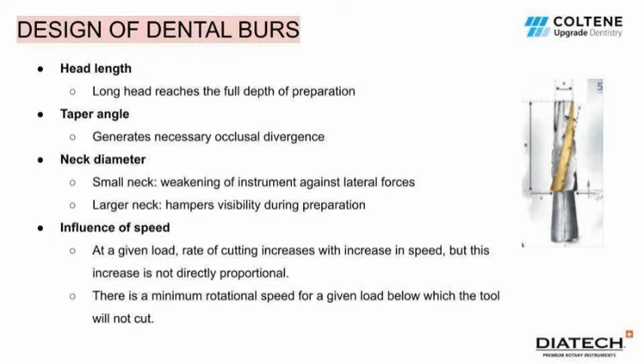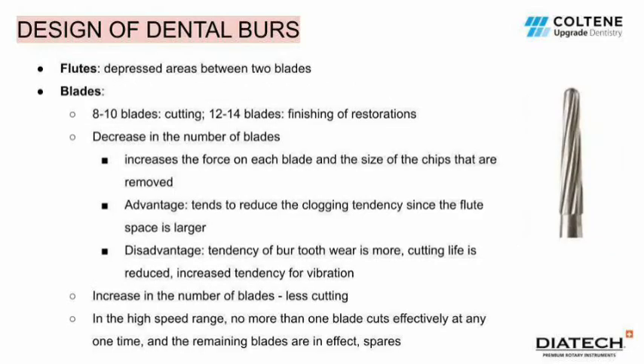After that, we have the influence of speed. At a given load, the rate of cutting increases with an increase in speed. But this increase is not directly proportional to the rate of cutting. There is a minimum rotational speed for a given load below which the tool will not cut. The flutes of a burr are depressed areas between two blades. Now, a burr can have different numbers of blades. For example, 8 to 10 blades is generally the range used for cutting burrs, while 12 to 14 blades are generally in burrs used for finishing of restorations.